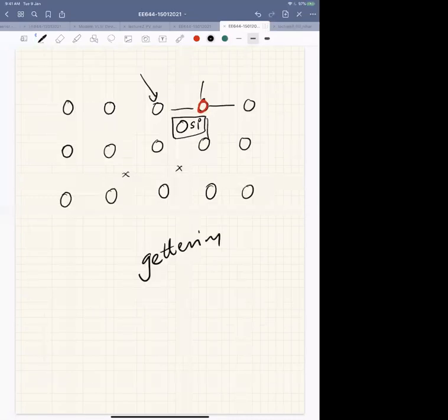So unless you anneal it, it will not become N-type or P-type, right? To become N-type, the arsenic has to move to the silicon site. Similarly, to have P-type, the boron should replace the silicon in the lattice site, the substitutional site, right? So that's the reason implantation is always followed by annealing, and you have to do proper annealing. You have to heat it for a certain time, and if you cannot heat it for that time, then it will not be activated, right?